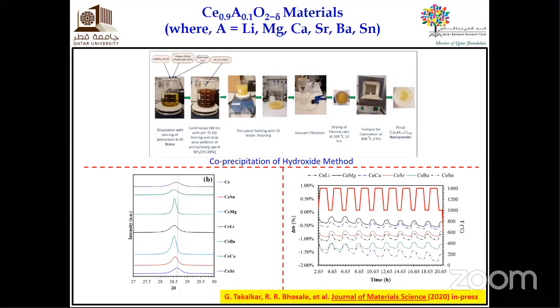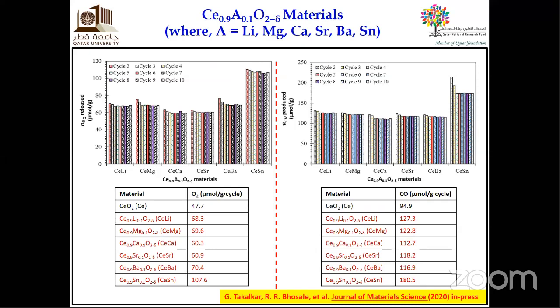The third one, which we did, is the remaining, for example, lithium, magnesium, calcium, strontium, barium, and tin from different sections. Here again, the same approach was applied because we want to compare them together. The thermal reduction was carried out at 1400 degrees Celsius and the splitting was carried out at 1000 degrees Celsius. Here, the things are more interesting because all the dopants successfully helped ceria to improve both the thermal reduction capacity and the CO production capacity.